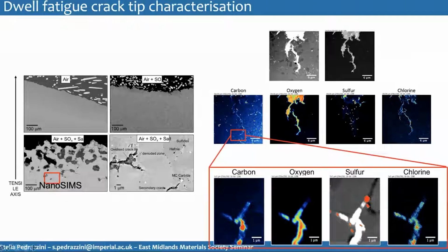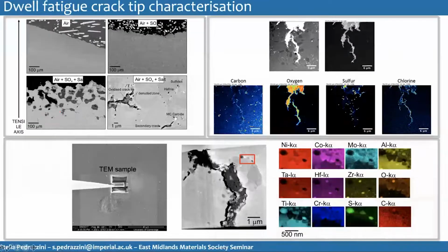And this is a more zoomed in version. You can see that there's not really even a gradient of sulfur going from the crack. There's just these particles that have formed ahead and around the crack, but it's not inside the primary crack. I needed to explain why, so I decided to go for TEM this time.